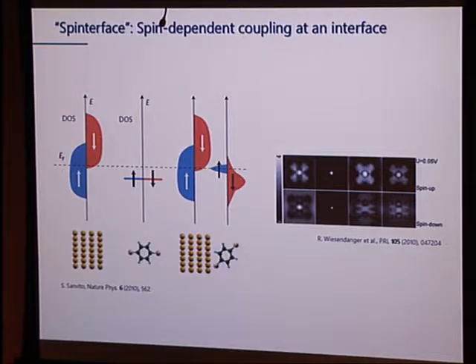If you look on the left-hand side, we have our ferromagnetic electrode with a split density of states, and we have this molecule, just an arbitrary molecule, that's a long way away from the surface, where the two different spins are degenerate. But by the time I bring this molecule close to the surface, a number of things happen. First of all, the energy levels change because of the renormalization effects I told you earlier. They shift, but they shift differently depending on spin. That's because they interact differently with the two exchange split densities in the ferromagnet.